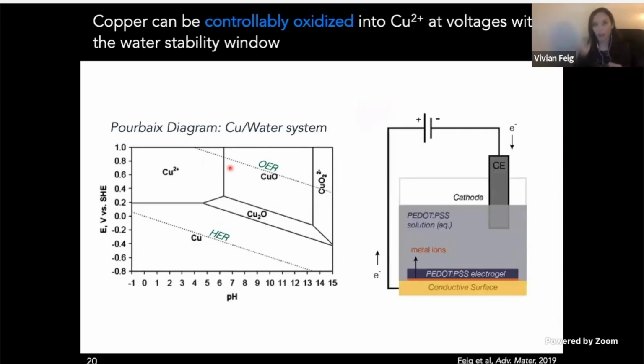So then with this copper-coated surface, we can use that as a working electrode within this cell where the electrolyte is the aqueous PEDOT:PSS solution. And so we just apply a constant voltage somewhere within this window, and that oxidizes the copper layer into metal ions that result in the generation of these PEDOT:PSS hydrogels.